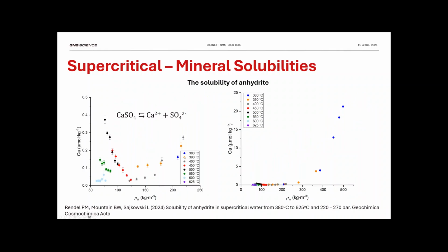And these are results for anhydrite, because that's another mineral that's probably really important when looking at scaling. This was published in Geochimica et Cosmochimica Acta last year. This is from 380 to 625 degrees and 220 to 270 bar. Note the concentrations. These are parts per billion concentrations. Very, very difficult. You can see these data here are all compressed down into this area in this diagram.